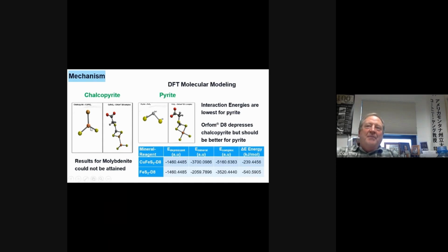With chalcopyrite, the copper is at the surface, as we're showing it here. The iron and the sulfur are subsurface. And with pyrite, the iron's at the surface and the sulfur's subsurface. So if this were flipped around and the sulfur were at the surface, then you would expect that surface to be hydrophobic. So if you give this some slight oxidation, you can make these surfaces metal deficient. In that case, the sulfur moves to the surface, and you can actually get collectorless flotation.